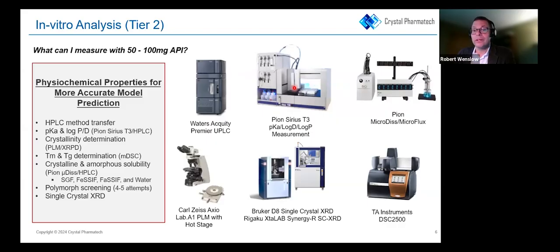Then we can start doing some forced degradation. And we're not talking 14-day forced degradation. We're talking, is your API going to blow apart with acid or base or oxidative or hydrolysis? So like a 1-day forced degradation, starting to play around with the HPLC method, starting to look at what impurities are coming in. From our end, we're not going to be doing necessarily mass spec and figuring out the structure of those impurities, but we do want an understanding of how your material is going to degrade, and maybe what solvents you want to avoid in your crystallization processes.